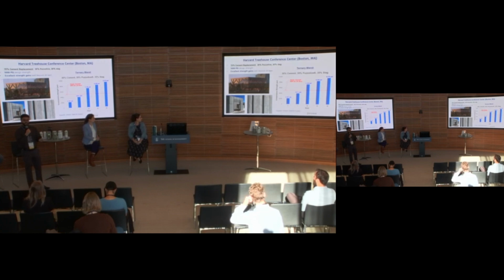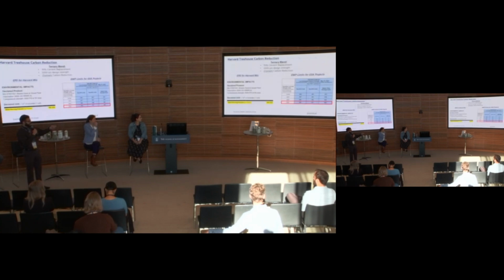So this is the Harvard Treehouse Conference Center, just to show a little bit of the performance as well. This is a 70% replacement in a ternary blend, 3 cementitious materials: cement, slag, and pozzolan. So a really high replacement of your cement to reduce carbon. You could see the strength gains there over 90 days, really good strength. And just to show, it's only 160 kilograms of CO2 per cubic meter of that concrete. And you could see on the right there, the General Services Administration sets global warming potential limits. For a 5,000 PSI mix, the top 20 percentile is 305 kilograms for your GWP. We're roughly half that with this mix at Harvard.